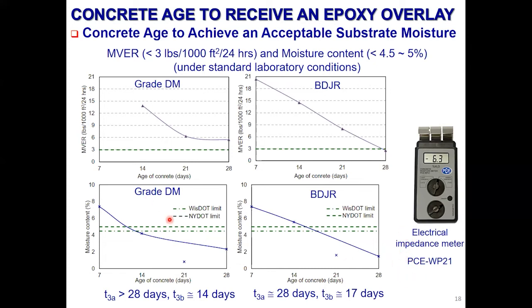With this, we evaluated moisture content in 2 mixes as well as the moisture vapor evaporation rate. When we look at the moisture vapor evaporation rate under laboratory conditions, with the slag mix we never reach that limit. That's strange. With type 1 cement, we could. But when we look at the moisture content, we can achieve that 4.5 or 5% limit within around 14 days in the mix with slag and about 17 days in the mix with type 1 cement. So we can go with specifications that specify moisture content as a limit to apply overlays.